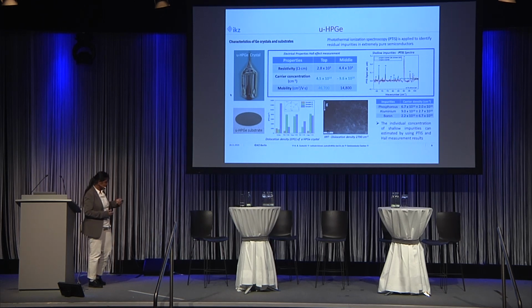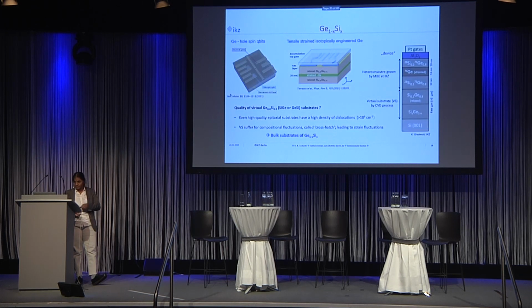for germanium. And also we have a very unique technique called photothermal ionization spectroscopy to identify what type of impurities are in our material and how we can estimate their concentration, together with the Hall effect measurement. And also the defect density is very low, in the order of thousands. It is very, very low when compared to the epitaxial layers, and so these crystals will be very useful as substrates for devices.